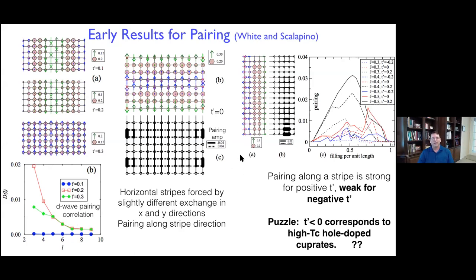Okay, and then in the center figure, it's interesting to try to get the stripes to run longitudinally. My cylinders are always laying flat. They're connected at the top and the bottom. So here are two stripes in a width 8 system that are running longitudinally. That's interesting because there had been earlier complaints that maybe all of the stripes I was seeing were just Friedel oscillations. But there are no Friedel oscillations if they're running longitudinally.